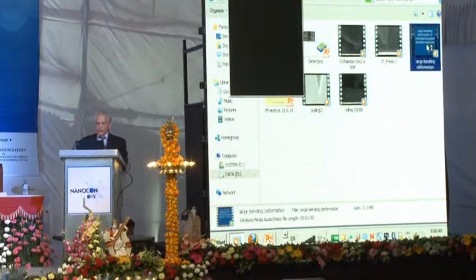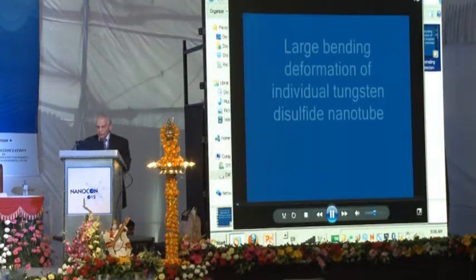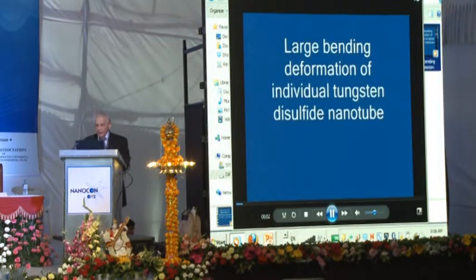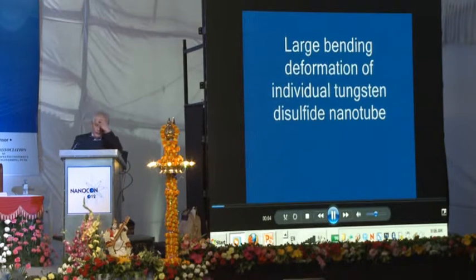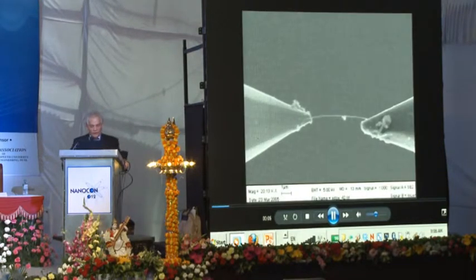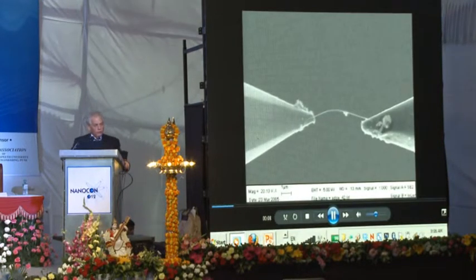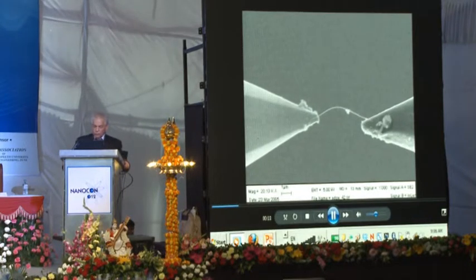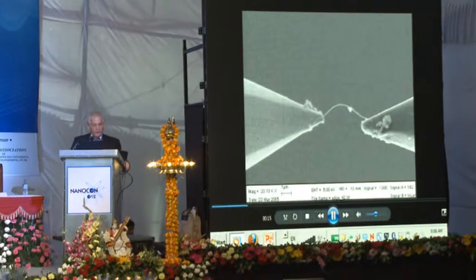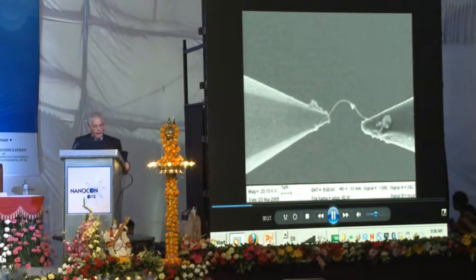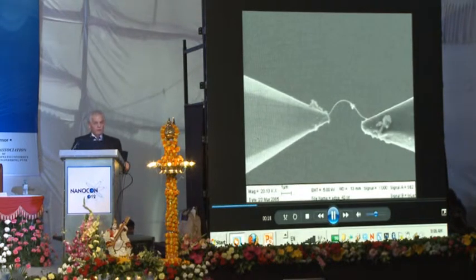And perhaps the most exciting movie is this one, which I'll show. This is the bending of this nanotube. This is a nanotube glued at the edges to 2 AFM tips, and now we push them face to face, and we try to break the nanotube, and it won't break. It's very strong, very flexible.